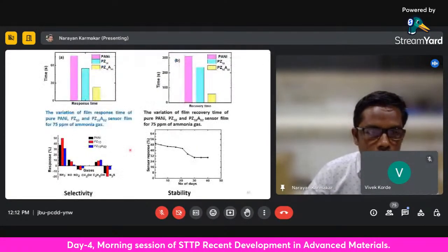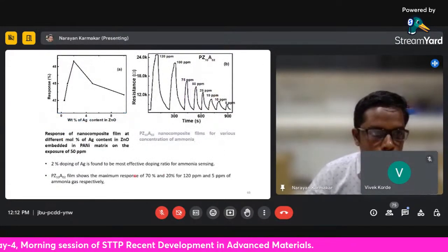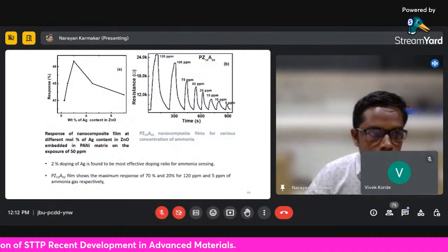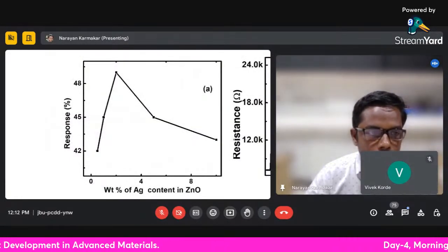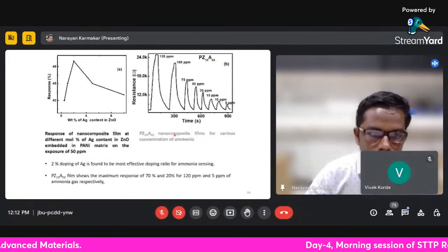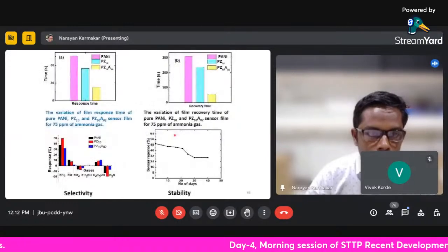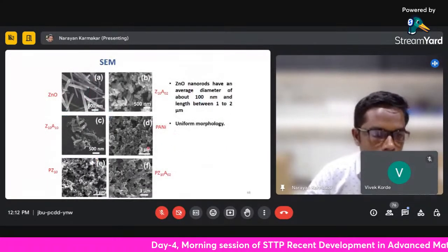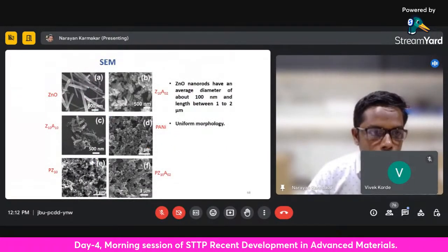But the question is this: why after 2% doping was the sensor response decreasing? For that reason, what we did is we studied the SEM image of all the samples. So look at the SEM image.